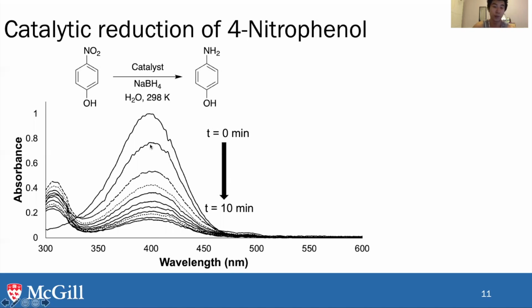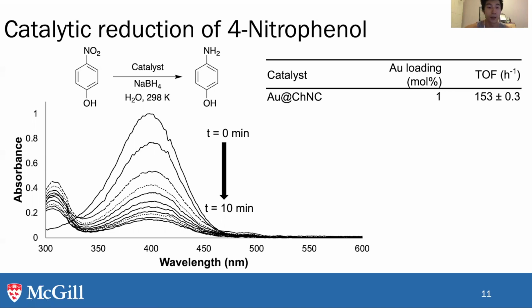So by using the absorbance intensity here, we can actually plot the turnover frequency as well as the rate of the reaction with this. So first we tried with the chitin nanocrystal. From this, using gold, we can see that it gives relatively high turnover frequency numbers. However, if we convert it and compare it with bulk chitin, you can see that the bulk chitin actually provides lower turnover frequency numbers. So this correlates to the fact that we need the nanoscale nature of these nanocrystals for higher dispersity of gold and therefore more activity.